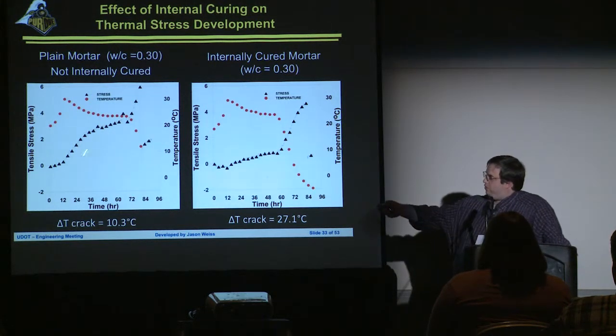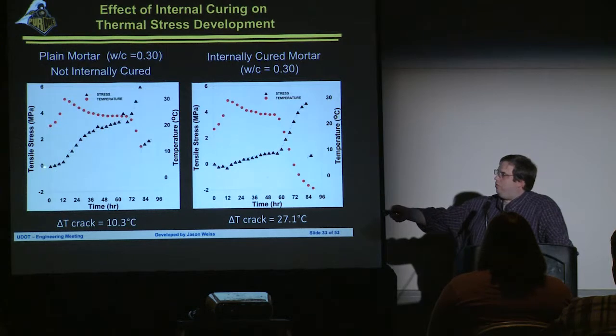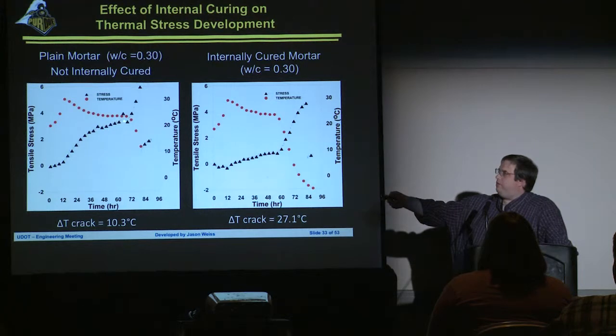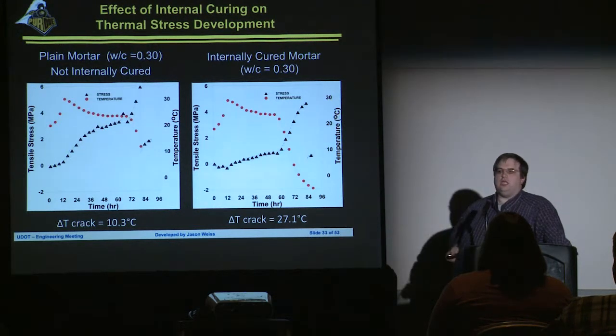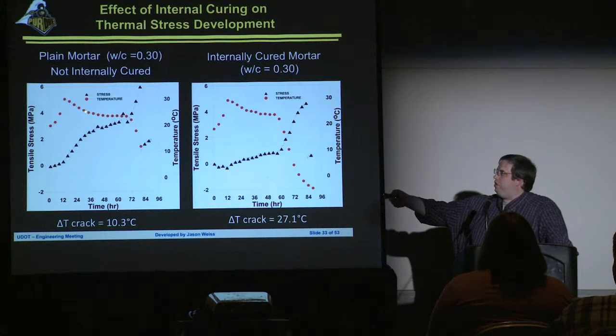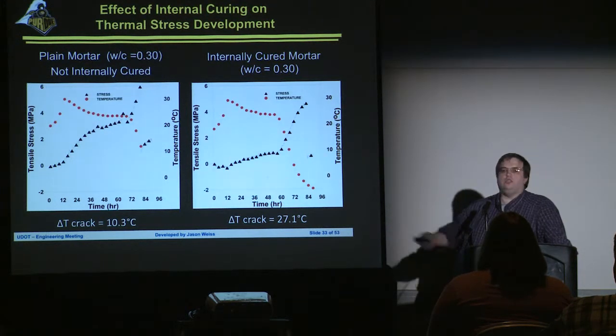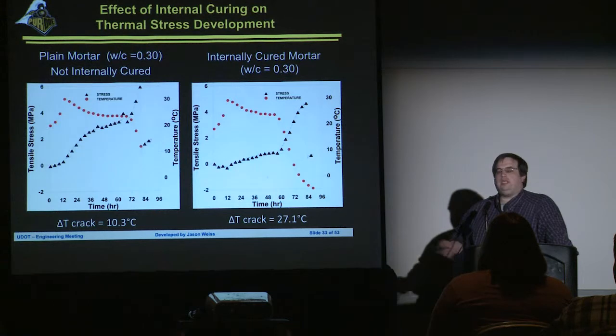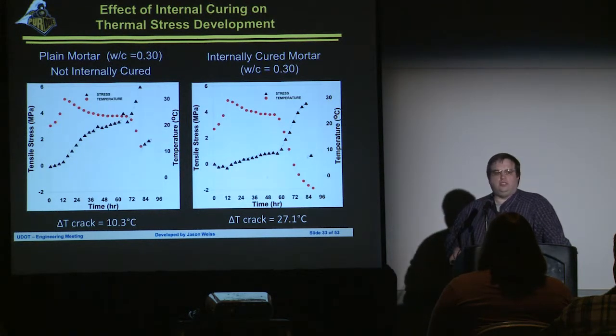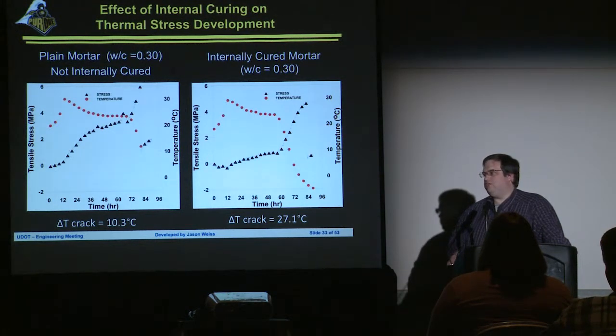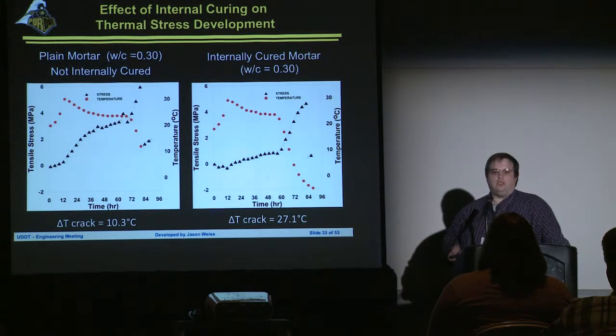So what I want to do is focus over here on a pretty typical bridge deck. And what we can see here is that we would see stresses starting to develop. And at some point, these stresses really start to take off. These stresses start to take off because at 72 hours, we started to drop the temperature. It took a 10 degrees Celsius temperature swing to get cracking in our conventional mix. Now you may say 10 degrees Celsius, that's about 20 degrees Fahrenheit. Can it change 20 degrees Fahrenheit from day to night in Utah? I think so. At 3 days, this bridge deck is going to crack.